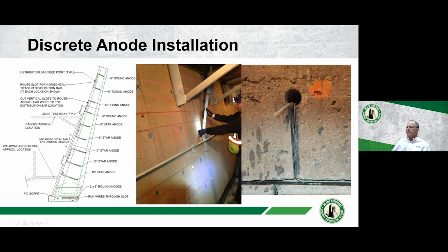the structure. Here you can see where the X's are, that's where they're going to drill holes, and all the red is the reinforcing steel. So you can see there's quite a bit of reinforcing steel that they had to navigate around. And this is a completed installation. You can see the vent tube, you can see the wire coming out, and here the titanium wire is spot welded to a current conductor bar.